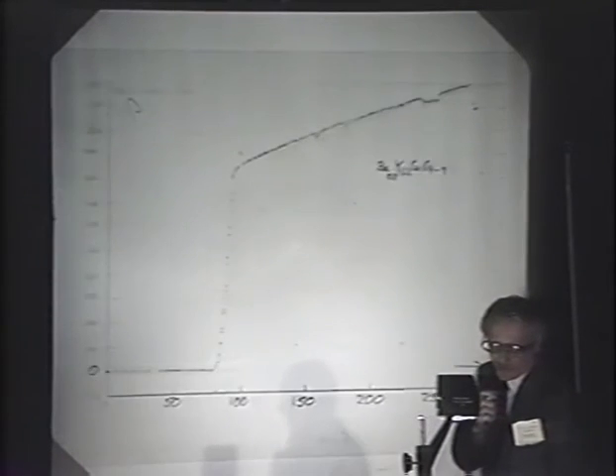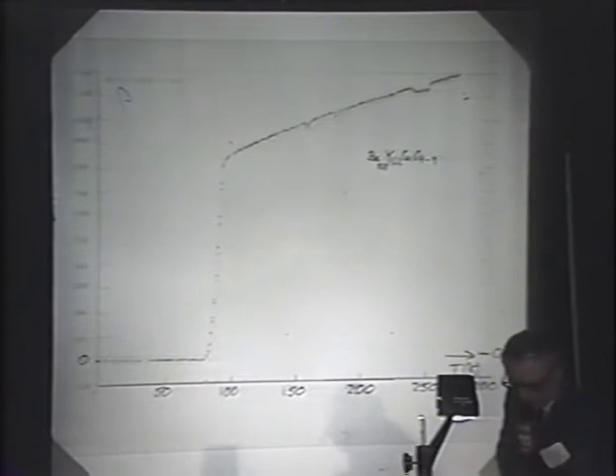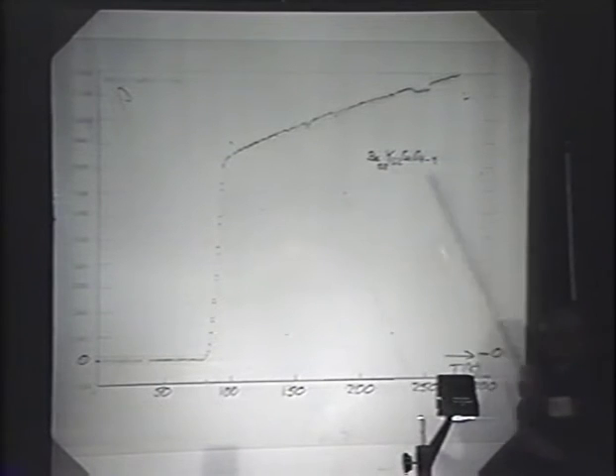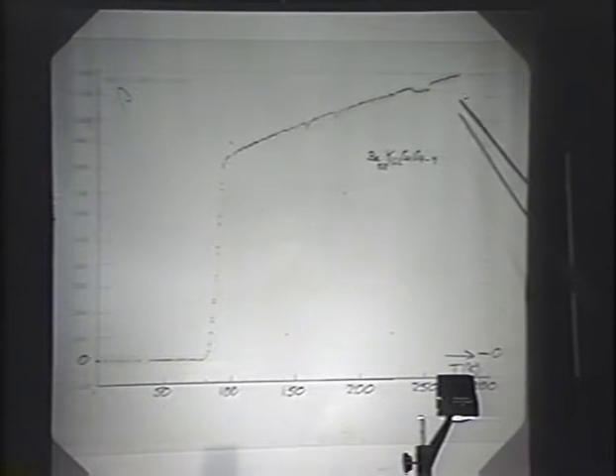Just about at this time, we learned, this time through the New York Times, because one of us was in New York, that there was another phase of this system which was going at higher temperatures. Let me show you one of Minovsky's samples, which is the multi-phase system, which shows indeed a very sharp transition, approximately at 90 degrees. And showing the raw data, there's another, perhaps more interesting, anomaly occurring at about 240 degrees, a tiny dip, which has been found in a number of other samples of this particular mixed phase. The other two triangles or other dips have not been very reproducible.